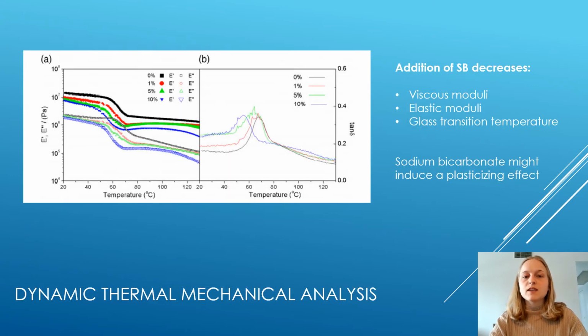They then did a dynamic mechanical thermal analysis. The important information that resulted from this graph is that the presence of SB in the blends decreased the elastic and viscous moduli as well as the glass transition temperatures. This shows that SB might induce a certain plasticizing effect.